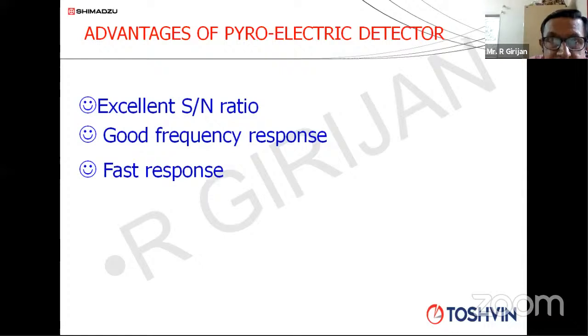Now that means the efficiency of conversion of heat energy to electrical energy will be maximum at the Curie point temperature. And if the temperature of the material goes beyond the Curie point temperature, the heat energy to electrical energy conversion efficiency will reduce. That means the sensitivity of the detector material will come down. So to avoid this, we have converted this TGS material into DLaTGS material, deuterated L-alanine doped triglycine sulfate. Why it is done is, a normal TGS material has a Curie temperature of somewhere around 48 degrees. If I remember correctly, around 48 degrees centigrade is the normal Curie point temperature of a TGS material.